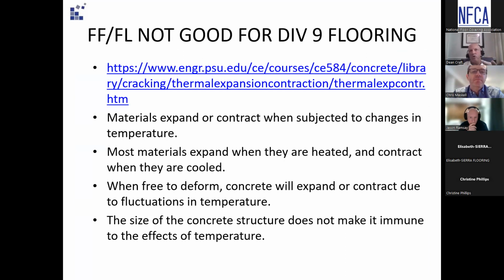Some of the things I want to point out, if you get to another project we're involved with: if concrete's placed in cold weather, a lot of times the concrete subcontractor doesn't cure, they don't protect it. You can still have massive evaporation in cold weather because the concrete could be warm. The concrete mix could be 80 degrees, going down, heat of hydration. The ambient temperature could be 30, which is not really that cold. And it's going to evaporate very, very quickly.